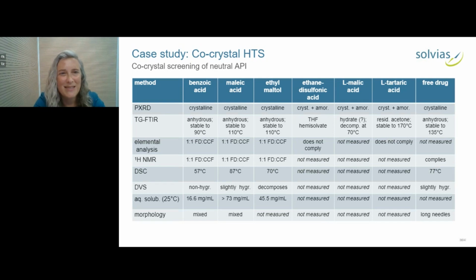And the results can be seen in this table. What you have are different characterization methods, the 6 co-crystal formers, the best example of each, and on the far right, the properties of the best form of the free drug. And then you can go through and start looking at things. So in 3 of the cases, we were not able to obtain a fully crystalline sample. It was partially amorphous. Maybe it would be possible with more work, but it's at least a little more challenging. So those are suboptimal. Looking at the TG-FTIR, 1 sample was a solvate, another decomposed at low temperatures. Again, maybe there's another polymorph with better properties, but we have better options.